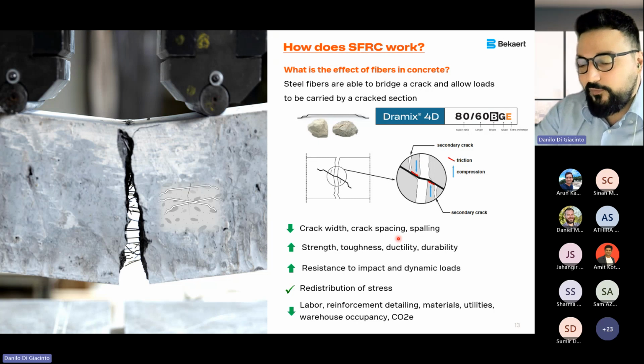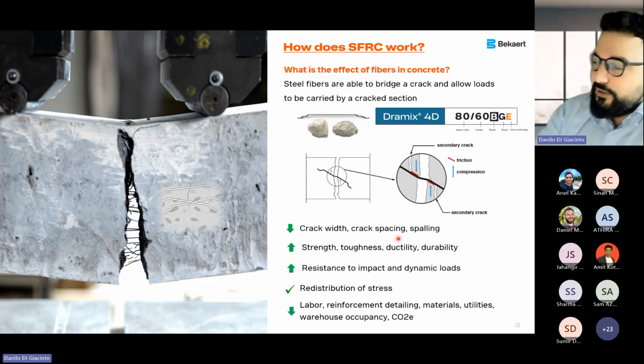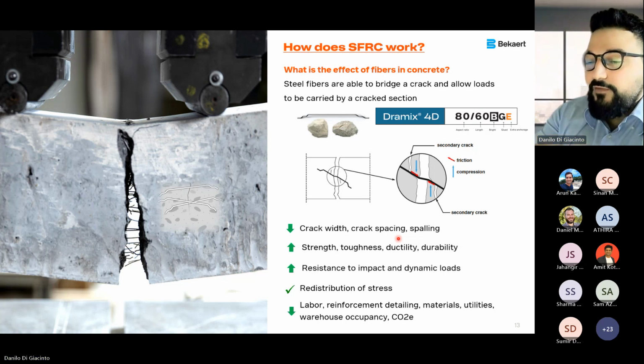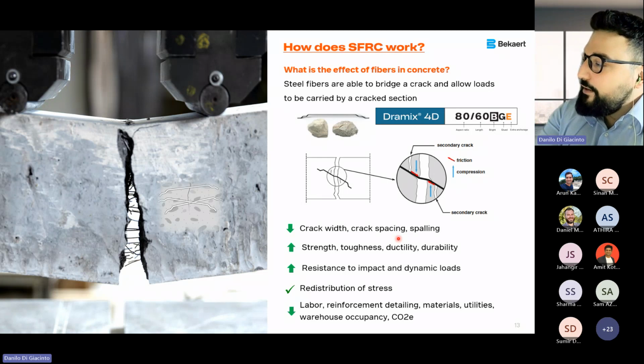Because the main difference from traditional concrete is that you don't have any unreinforced concrete cover. Even what you can call the concrete cover is reinforced, so durability is enhanced. Smaller cracks, cracks are more closed. The cracking mechanism is improved, so the durability of the structure is improved. Also, there is an improvement in resistance to impact and dynamic loads.